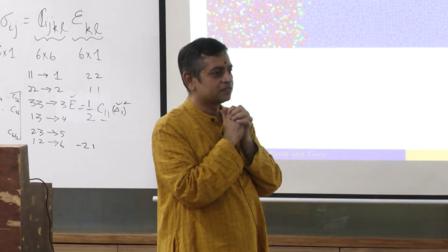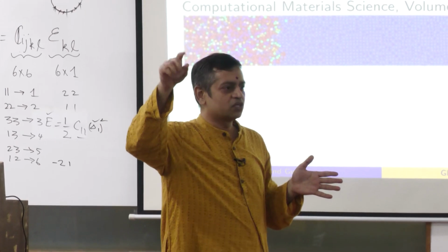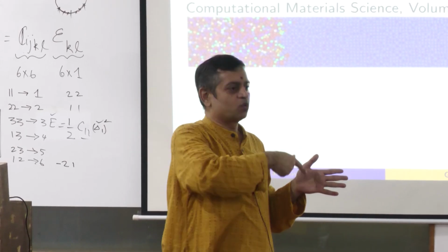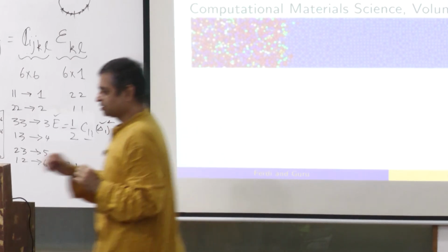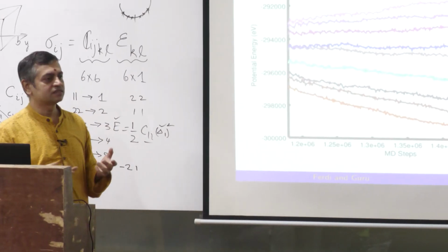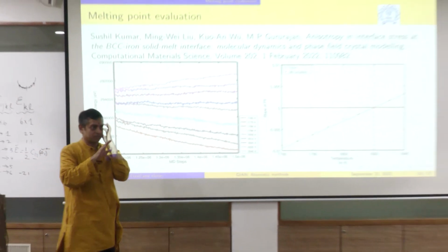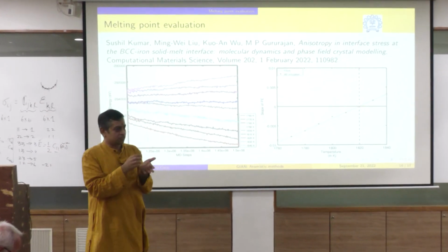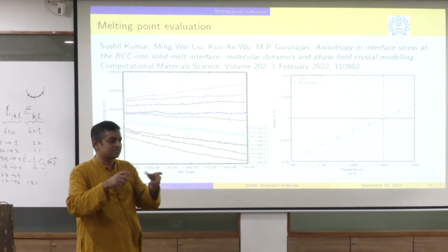For doing this, you probably had to run many simulations at different temperatures. Yeah. First you take a solid, start heating it up, note down where it melts, and then cool down, note down where it solidifies. So you know the range. Once you are in the range, then you only need to run several simulations at temperatures within it. Of course, it still involves lots of stuff. With temperature the lattice parameters are different, so you have to get equilibrium, otherwise those energies will also change.